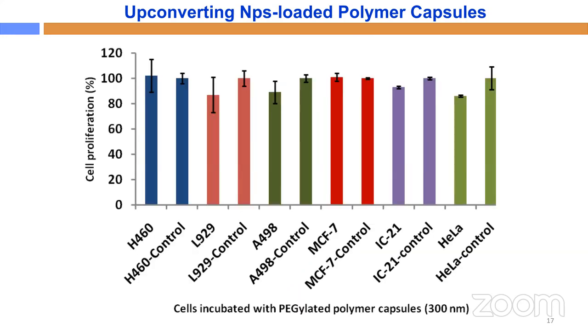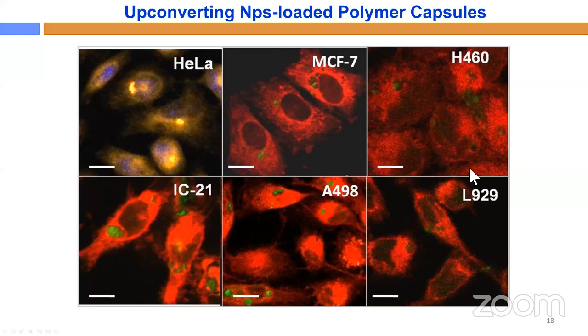Once this is done, then we want to know whether these nanoparticle-loaded polymer capsules are highly compatible. So we have done the biocompatibility study, that is called an MTT assay. All these graphs show that these nanoparticle-loaded polymer capsules are biocompatible. It shows lesser toxicity. Again, we have done the uptake study. All this red and green emission coming from the nanoparticle excited with 980 nanometer shows nanoparticles are uptaken by the cells.